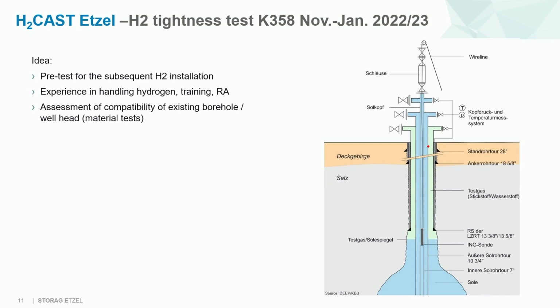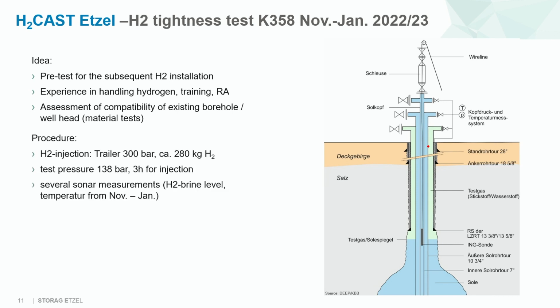So the 30-year-old material was suitable for hydrogen. And the procedure was quite easy. We injected hydrogen by a trailer with 300 bar, about 280 kilos, and then we had a test pressure of 138 bar. This was the maximum allowed pressure for the wellhead at this time, and we did several measurements from November to January this year.